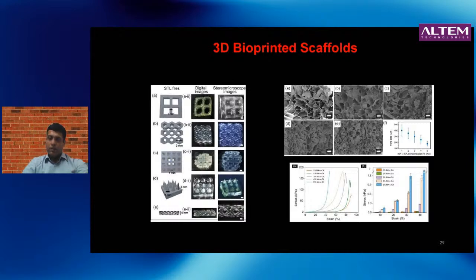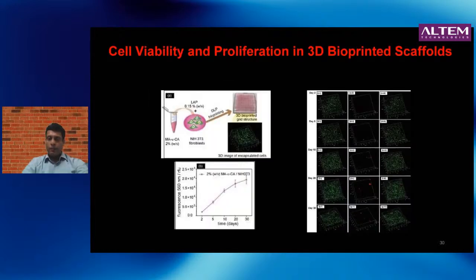We can vary the concentration of the polysaccharide from 1 to 5%. That, of course, means that at higher concentration, the pore size becomes smaller and also the stiffness starts to increase. Nevertheless, all of these scaffolds are great for encapsulating cells. So we have taken NIH3T3 cells and we have cultured them in these scaffolds. Particularly, I'm showing you data for the 2 weight percent pre-polymer solution that was used to prepare the scaffold.